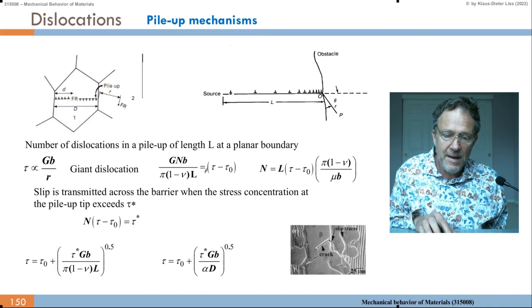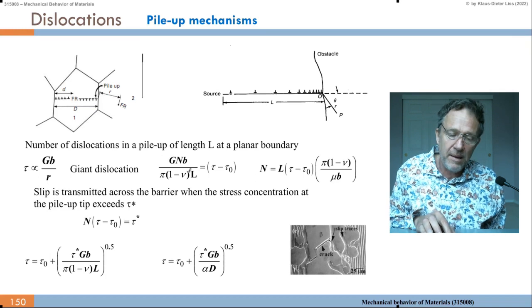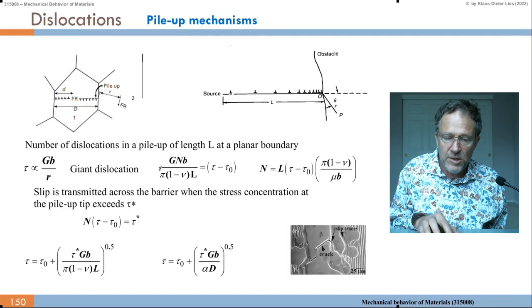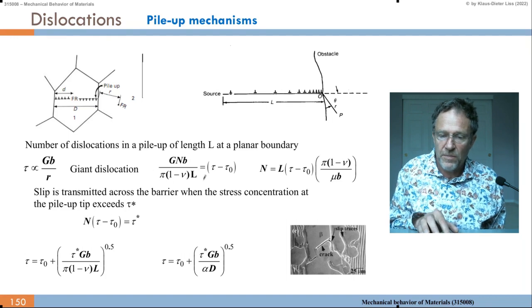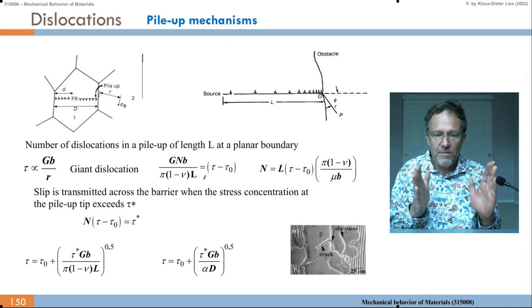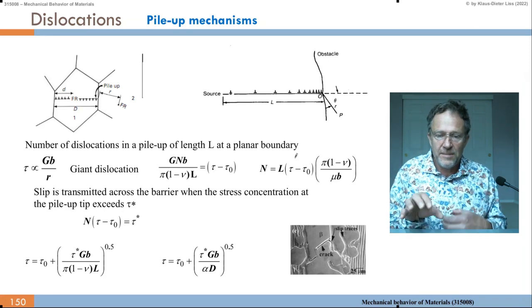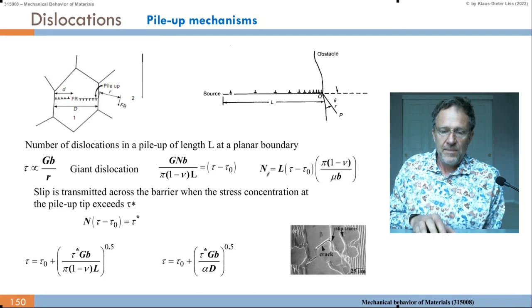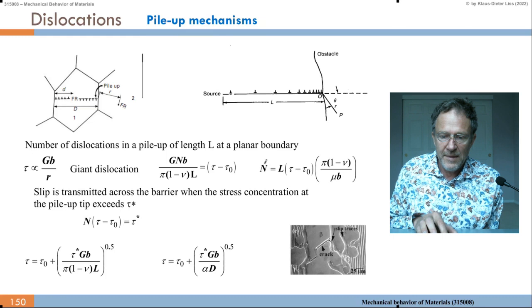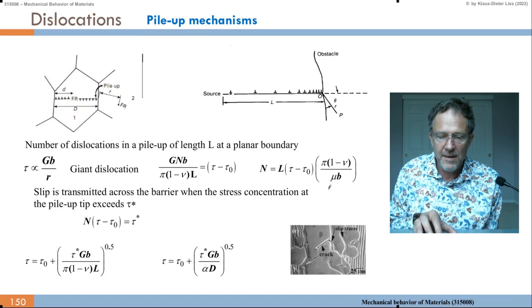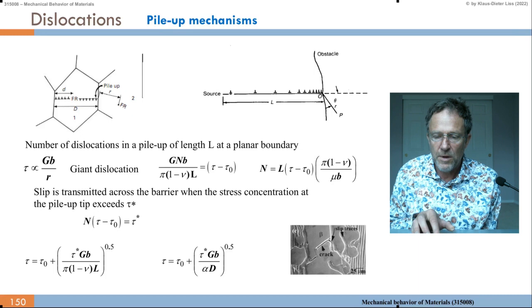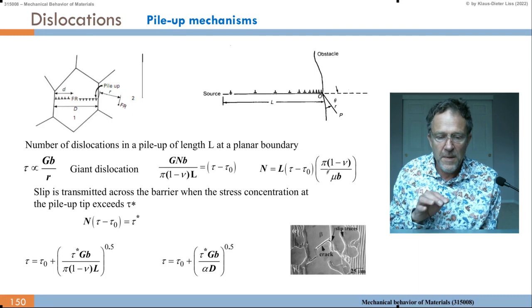And then it becomes larger. How much larger is given by G times n times b divided by a kind of radius, a linear dimension, which depends on the shape. And of course, if you compress in one direction, in the other dimension we have Poisson's ratio. And then n can be written as L times (tau minus tau 0), so put the L here. Then we have pi times (1 minus nu) divided by G times b. So mu equals G. This formula has been copied and pasted from different sources apparently.